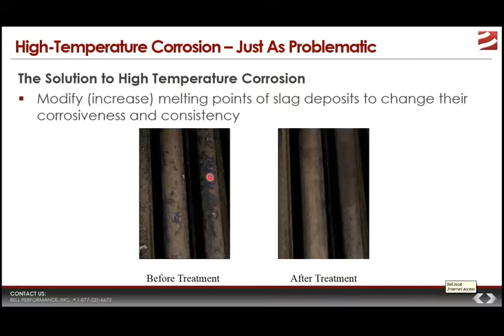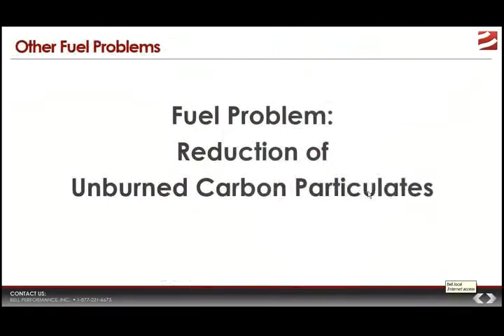Before, they had these characteristic corrosive, almost pitting damage on their high temperature tubes. This is in the hot zone, the high temperature zone. When they used the magnesium treatment, it actually fixed this problem. And this is what those tubes look like after a certain amount of time with that treatment. So they added something to the fuel oil. It caused the deposits formed to have a higher melting point, which made those deposits less corrosive and changed their physical consistency, making them easier to remove, so that their boiler tubes looked like this, not like this.